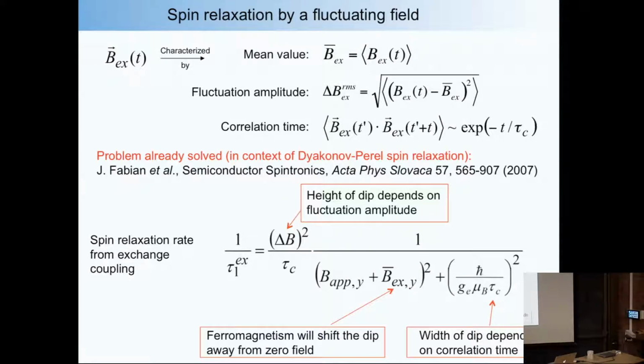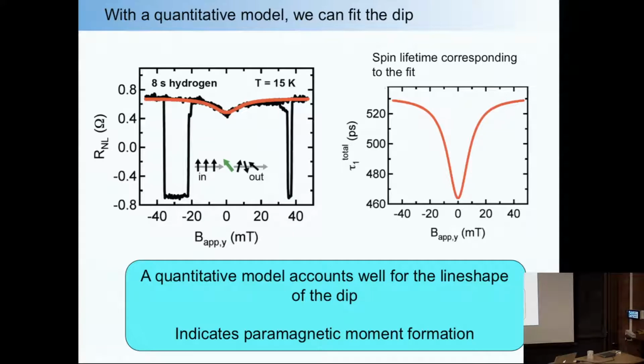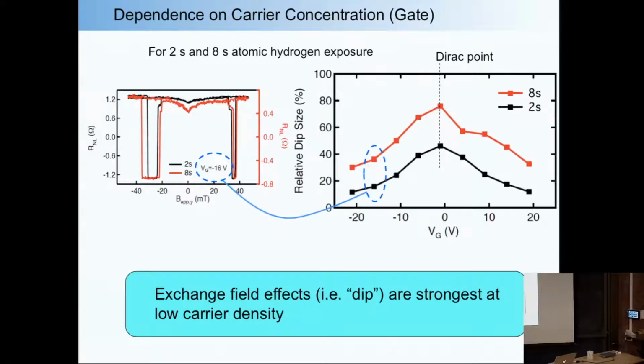But the point is, I take this type of model of a fluctuating exchange field, and you're able to fit very well, except for maybe at the very tip, the shape of the dip. And for basically every single dip curve we get, we have very good agreement in terms of the shape between the theory and the experiment. So it quantitatively accounts well for the line shape of the dip. And the other thing is that it indicates that these magnetic moments are paramagnetic. So we haven't seen any ferromagnetic ordering yet. Even today, we haven't seen it yet, right? But this is showing you something that's kind of neat.